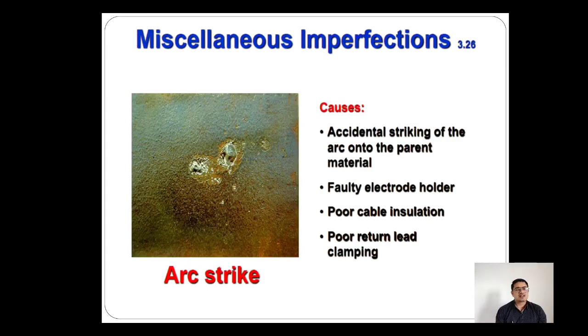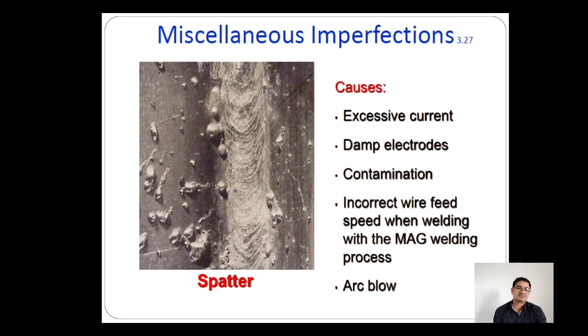So friends, this is arc strike. Arc strike basically happens when the welder strikes the electrode on the parent metal. This is very dangerous, because on the parent metal it creates a hot area at the particular location where he strikes. So the main reasons are accidental striking of the arc on the parent metal, a faulty electrode holder, poor cable insulation, and poor return lead clamping.